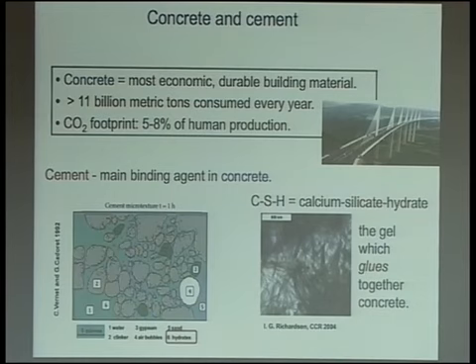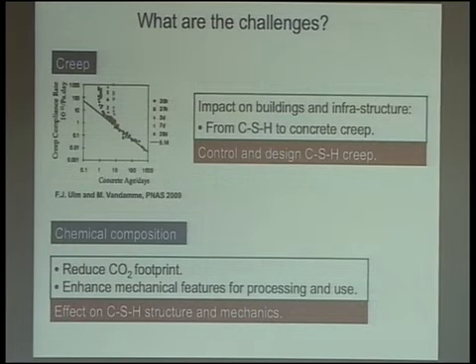So it's extremely fascinating for a soft matter scientist to think that this very hard material that you use to make bridges, in fact, most of its strength certainly, but also a lot of other mechanical properties, depend on this initially soft nanoscale disordered gel. And the thing is that this material, the CSH, has of course been intensively investigated over the last 100 years probably, but because of the complexity of the material, and because engineers are of course more focused on the macro scale, there is still very little understanding of the basic mechanisms that control the hydration and the development of the properties of the gel, in spite of the fact that at the end the properties of the gel are what you want to control.